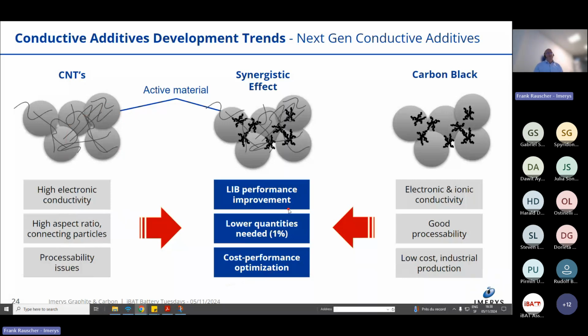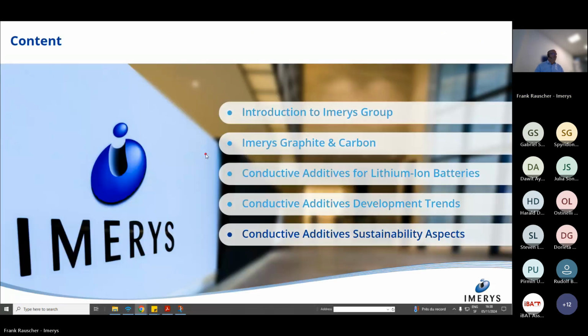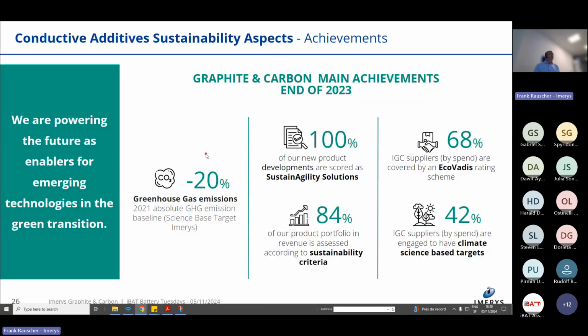Again, if you combine that, you work with a dispersion in which you have carbon black and CNT, and this allows you to basically tailor the performance of your conductive additives. Are you a customer who looks for a better cost proposition, or are you performance oriented? That determines how much CNTs and carbon black you use in such a blend. Low quantities are needed, and as I said, you can optimize it according to your needs. Now going to the last topic, and I see that I'm okay in time.